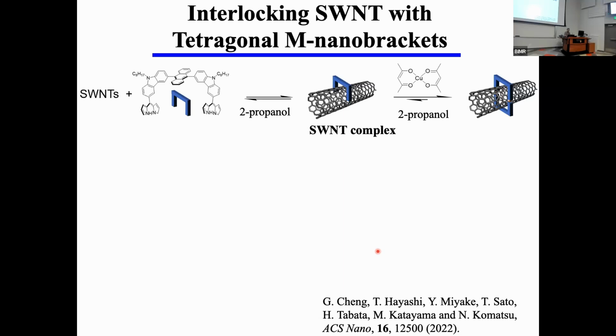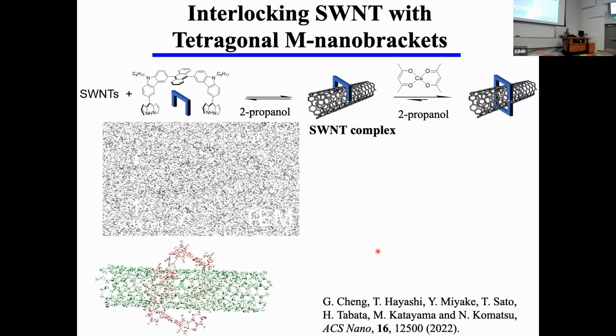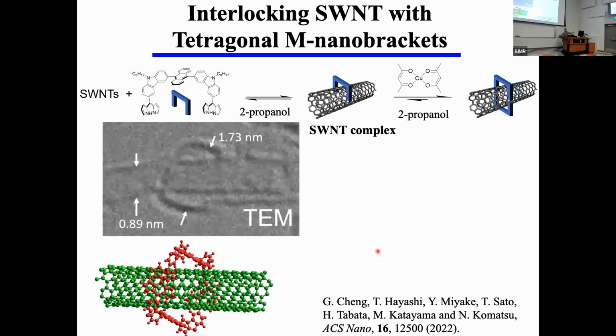First, we mix the carbon nanotube with a nano bracket in 2-propanol as a solvent and sonicate, and this shallow nanocaliper also forms a not so stable complex, but when we add the copper, it interlocks the carbon nanotube like this. And this is one of the pieces of evidence of interlocking the carbon nanotube.